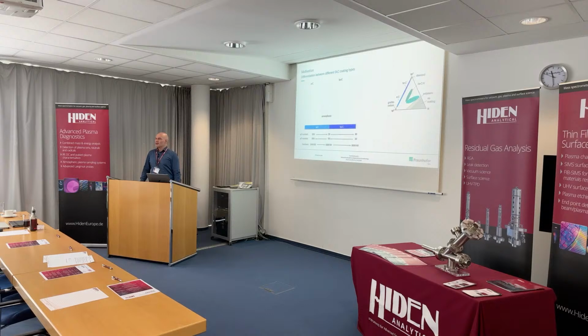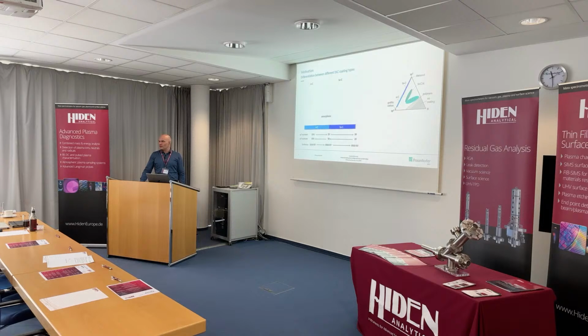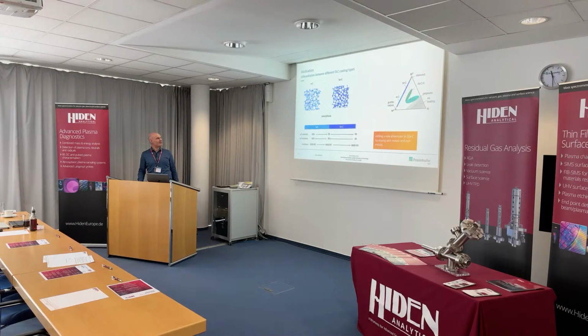Now the picture is missing. It's in the range of SP3 content from 20 up to 80. This is one advantage of our technology. We can get these kinds of hard coatings, especially in very high rates. And of course, we are hydrogen free or nearly hydrogen free. We don't have it in the chamber. Maybe if there is some leakage, then we have some very small amounts, but no hydrogen in the coatings at all. So at the end, we get very hard coatings. Maybe now it's back again, the a-C and ta-C. You see the different bonding types. The darker ones are the SP3 ones, and the bright ones are SP2, the graphite-like bondings.